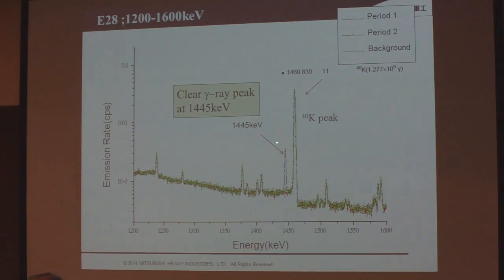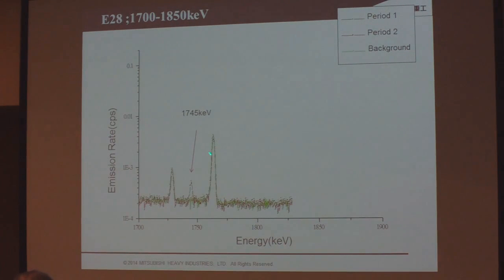But you can see a clear gamma ray peak at 1445 keV. And this is a K40 peak, potassium 40 peak. You can see this peak is very clear and stable. So this peak was emitted only in period 1 in the same sample. Also in period 1, we can see another peak at 1,745 keV. And other peaks we also detect in this case.